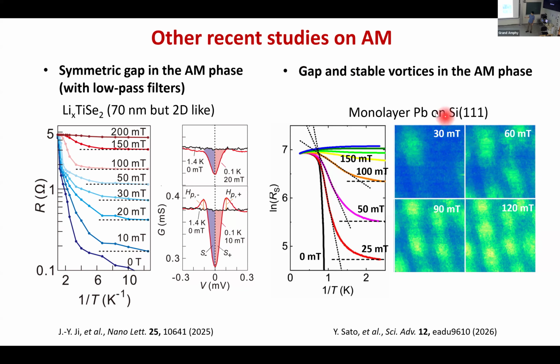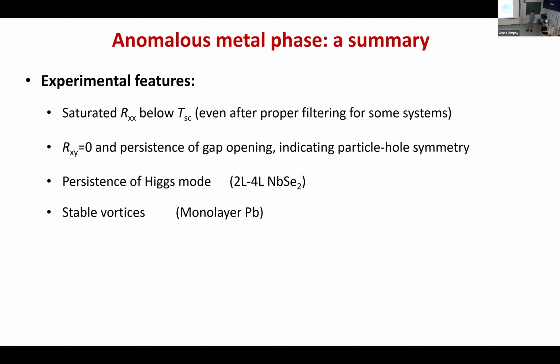And another recent work, they measured lead on silicon. And this is interesting because they try to combine transport with STM, so they measure everything in vacuum. So in the anomalous metal phase, they observe these vortices. So what they're trying to say is that, okay, the theoretical picture, just the last slide, we mentioned that you have these vortices tunneling. So these vortices should be moving around. You shouldn't be able to see any stable vortex, but they observe this. So this is experimental fact, but how to understand this, I mean, this is pretty new, so I think there's still something going on.